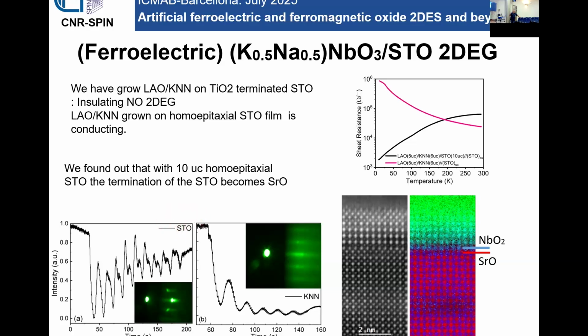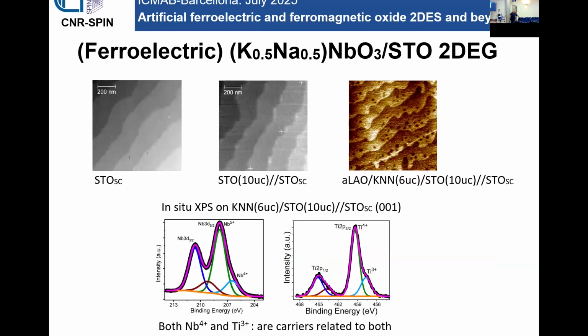Okay, then we performed in situ XPS to verify that the strontium is in excess at the surface. But the final word was that essentially the high-resolution transmission electron microscopy on this heterostructure shows indeed, when we grow an STO epitaxial film on top of a single crystal, a niobium oxide, strontium oxide interface. So it's a nice result. And this one is conducting, as you can see, it is a 2-dimensional gas. From the point of view of the growth and the morphology it is very nice, as you can see.